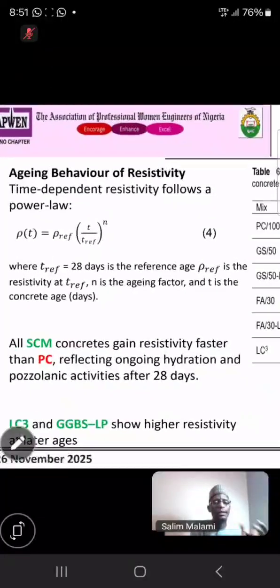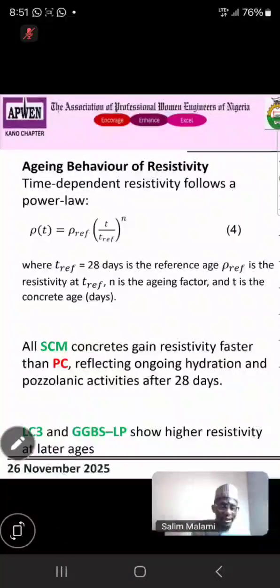The formula: this is the resistivity at the time you want. Let's say the time is 1 year, so this is P at 360 days. This is P-ref, the reference resistivity we took at 28 days. T is the time we took, like for 1 year, 360 days, over 28 days. Then n is what you call the ageing factor, the factor showing how resistivity is increasing over time. So in our own work, we calculated our own